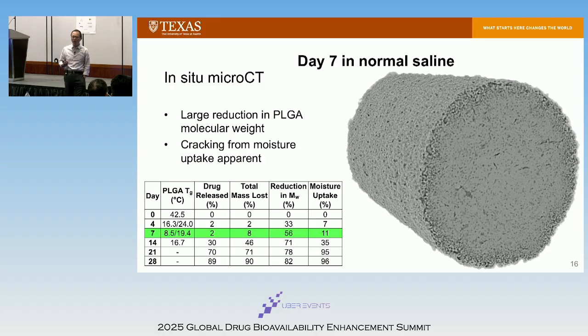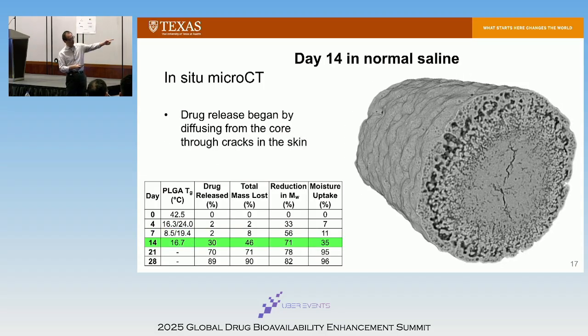And once they're hydrolyzed, it's self-catalyzed, right? Because when PLGA degrades, ester bond breaks to the alcohol and the acid. PLGA degradation is pH dependent. The lower the pH, the faster the degradation is. But then on the skin, there's a difference, right? If you look at the skin effect, obvious, right?